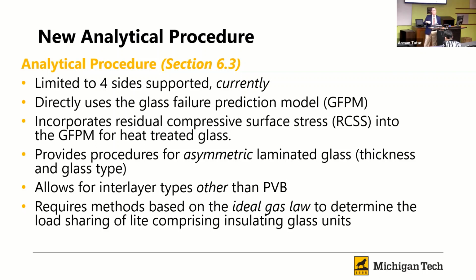The way the standard is written is that heat-treated glass has minimums for residual compressive surface stress for it to be considered either heat strengthened or fully tempered. And the standard requires you to use the minimums for design because you don't know what you're going to get. You've created a glass design, and then the contractor is going to go and find somebody to actually make the glass, and you don't have a way of knowing what residual compressive surface stress you're going to get. So we just use the minimums. But forensically, one could go back and check that if they wanted to.